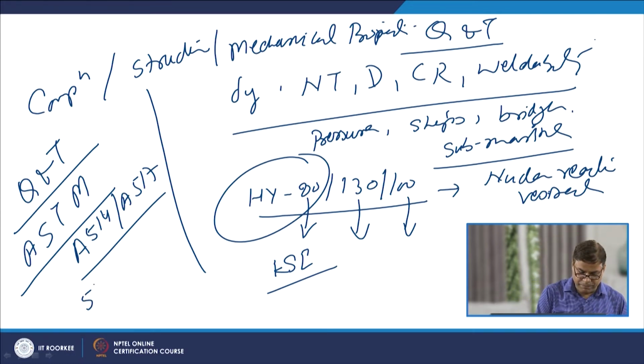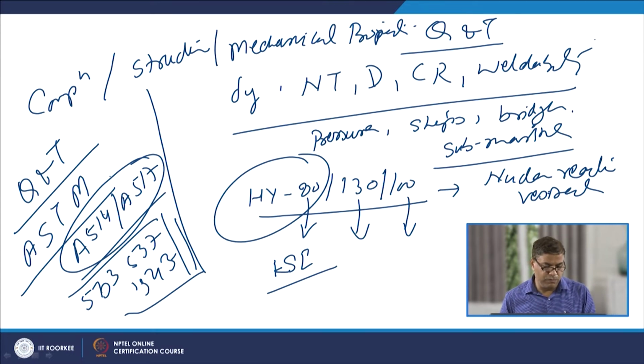Other steels are like A533, A537 and A543. These are other category of the steels, and they offer their own combination of the properties and the weldability, but this type of steel like A514 and A517, these offer the strength generally greater than 100 KSI. So, those high strength steels need very careful and very special precautions for developing the sound weld joints, so that they can perform successfully during the service.